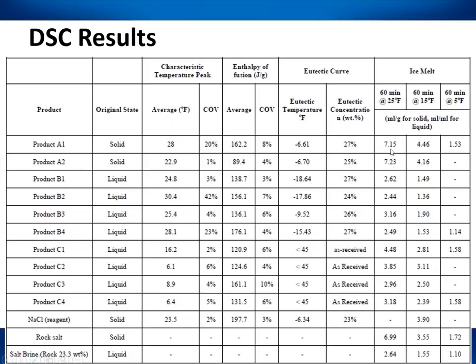And what you can see here is that at warmer temperatures, you get more ice melt consistently across the board. At colder temperatures, you're getting less ice melt. And then at 5 degrees, regardless of product type, almost all the ice melting rates or ice melting capacity is about the same. And that's kind of important, especially when you're talking about complex chloride mineral-based products only working to a certain temperature.